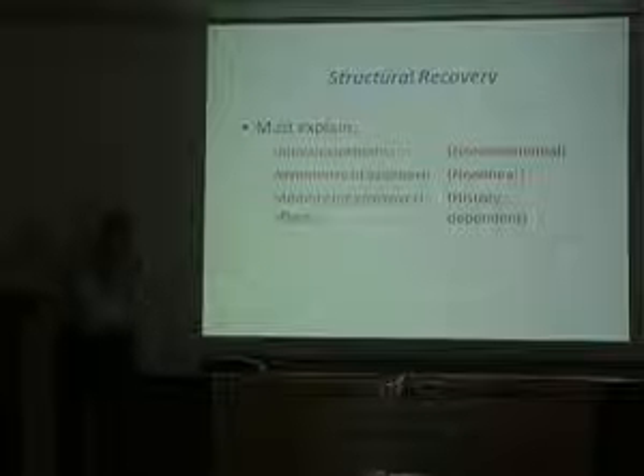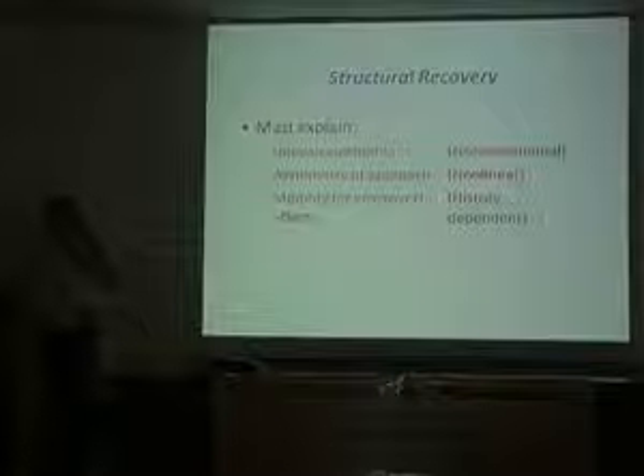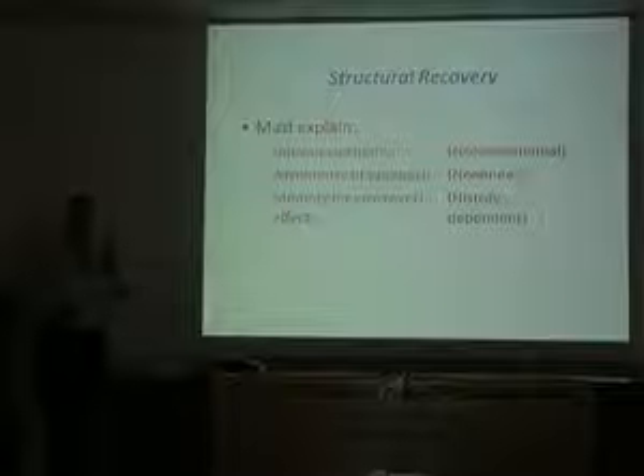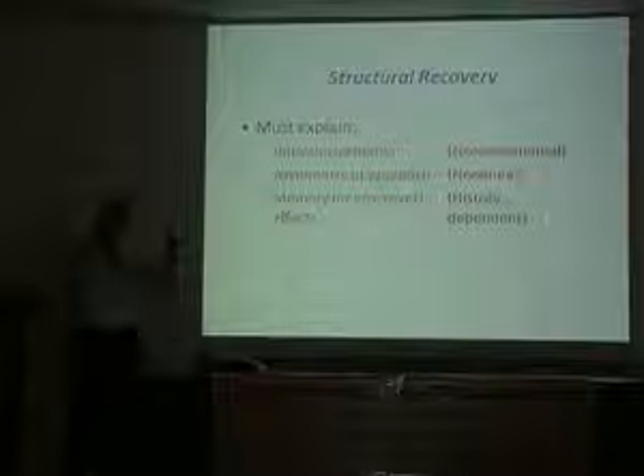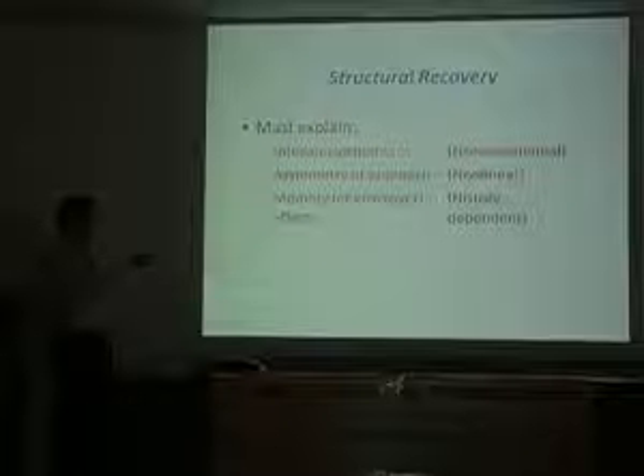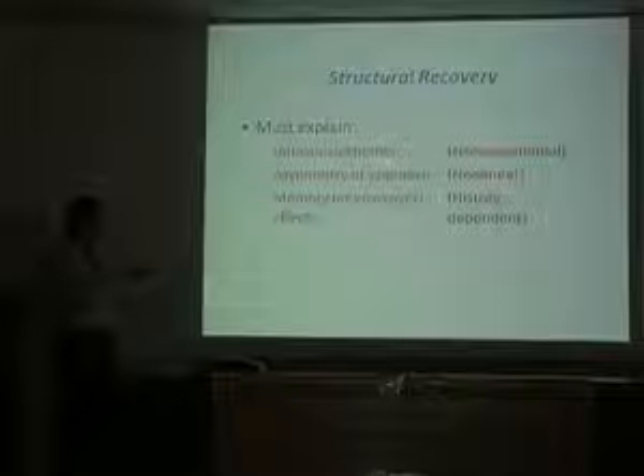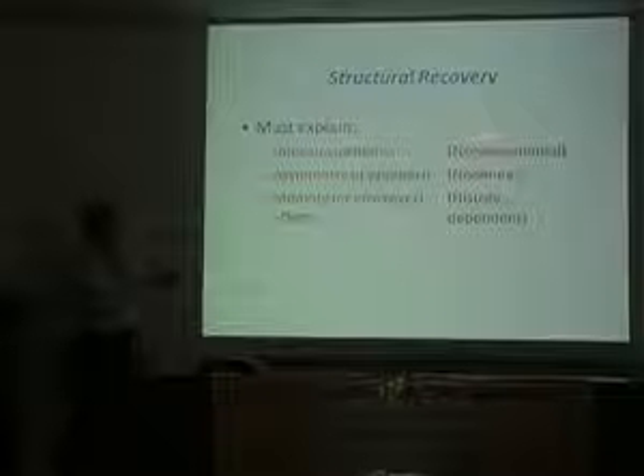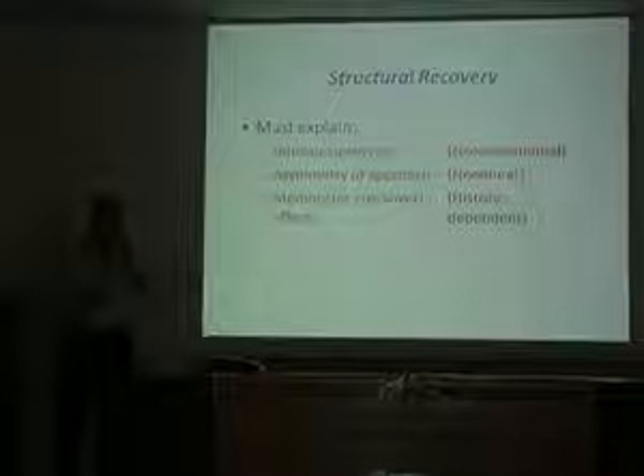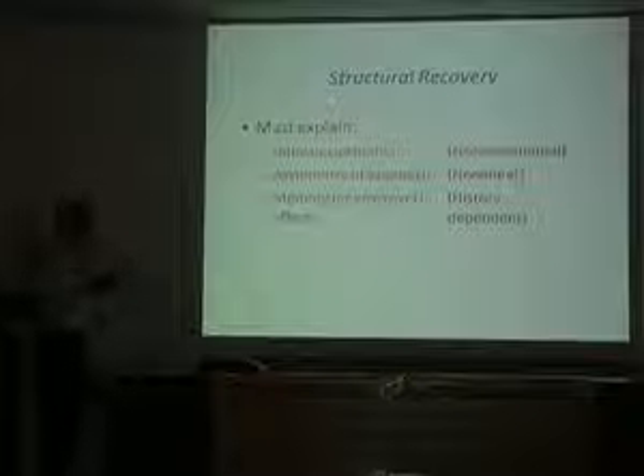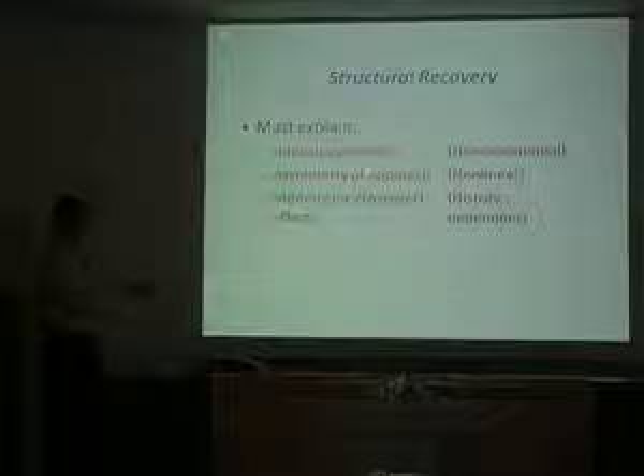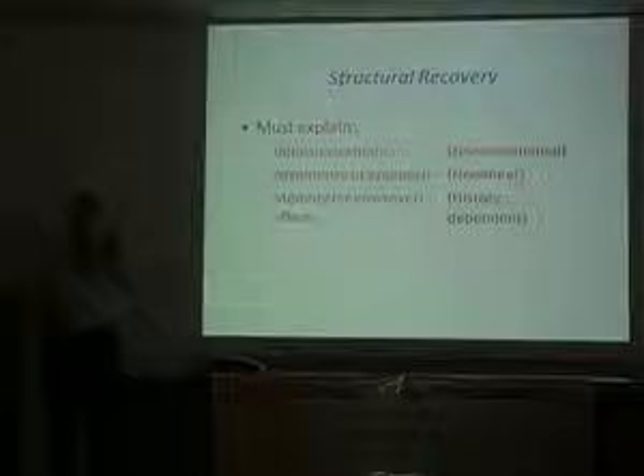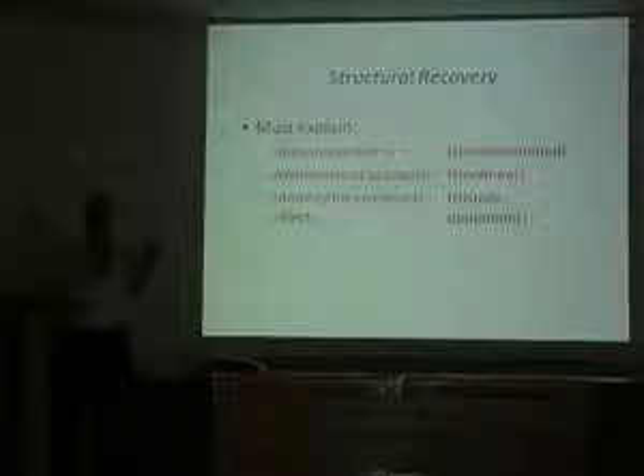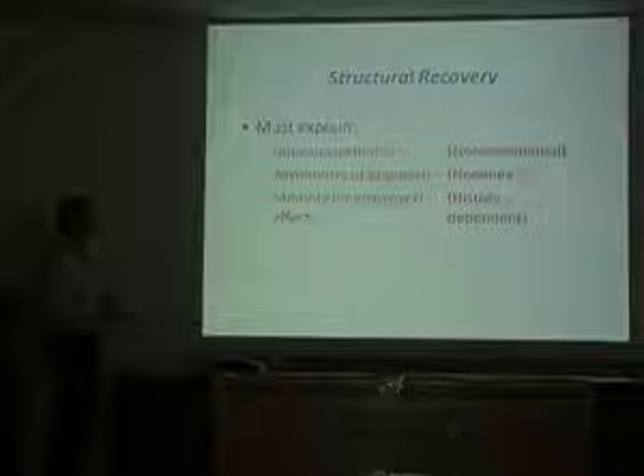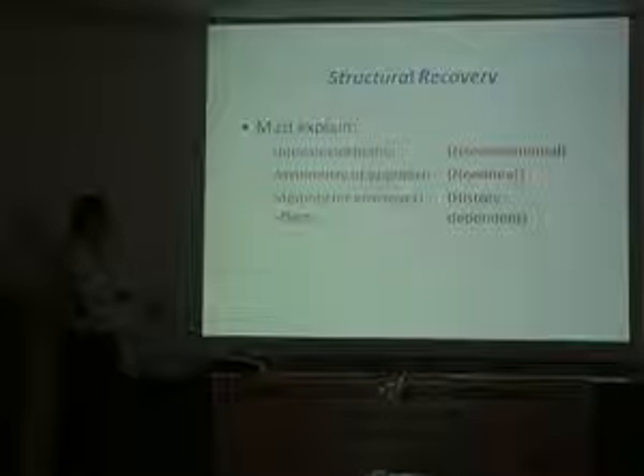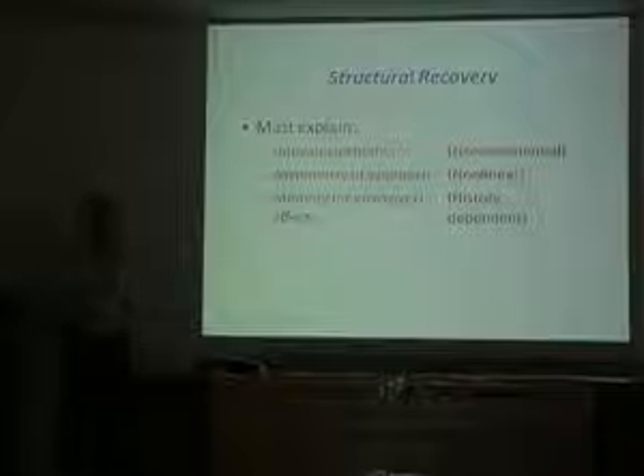So, glass transition kinetics. What does it have to explain? I mentioned that Kovacs had cataloged this back in the 1960s, and these things weren't original per se to him, but he did a nice job of cataloging the behaviors. It's what we call the intrinsic isotherms, and the intrinsic isotherms are clearly non-exponential in their response. So we often think of a KWW function. Kovacs thought of sums of exponentials, but it's not a single exponential. Asymmetry of approach, and we'll show what that means, shows the nonlinearity of the process, and I'll show what the explanation for that is. And the memory or crossover effect shows the history dependence, and it shows the non-exponentiality. Okay, and I'll tell you what I mean by that.